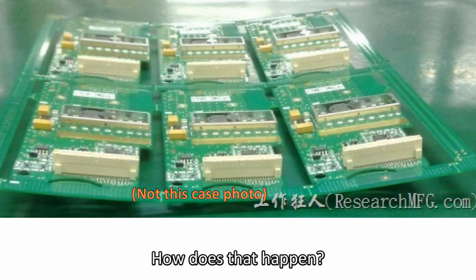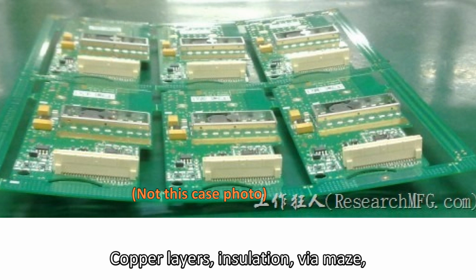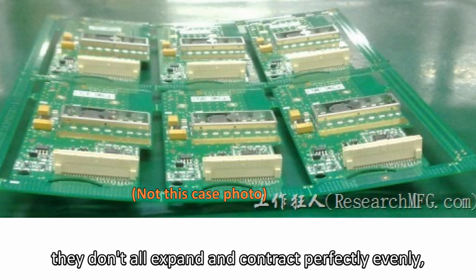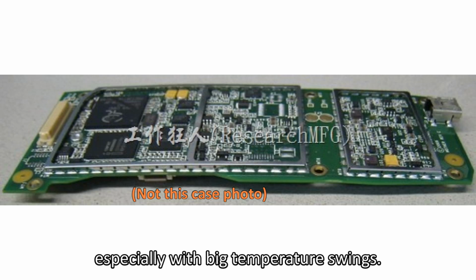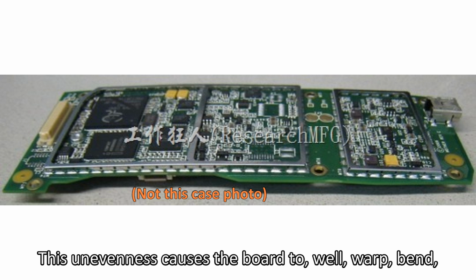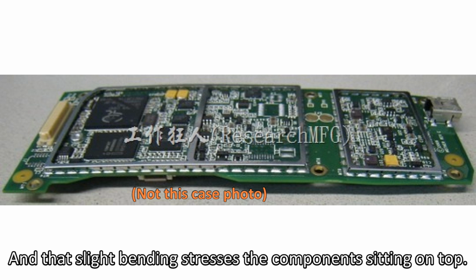Warpage? How does that happen? Multi-layer boards. They're complex structures. Copper layers, insulation, vias maze. They don't all expand and contract perfectly evenly, especially with big temperature swings. This unevenness causes the board to, well, warp, bend, flex, twist slightly. And that slight bending stresses the components sitting on top.